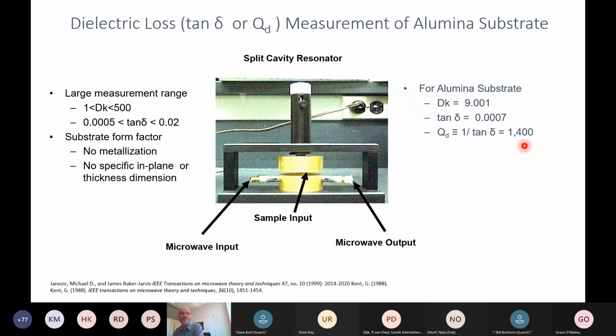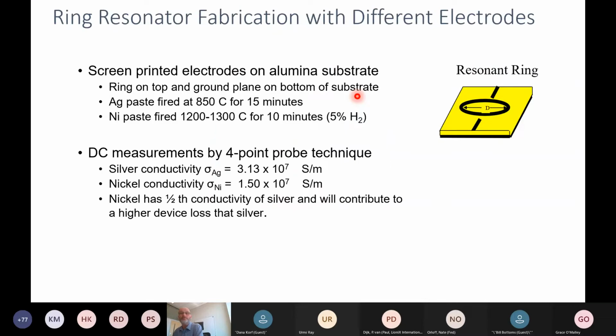If we look at the Q factor, very high. And so this is our substrate for our ring resonator, measured independently. And so we can use that to back out the conductor losses. So this is an experiment that we did where we screen printed on different conductors.